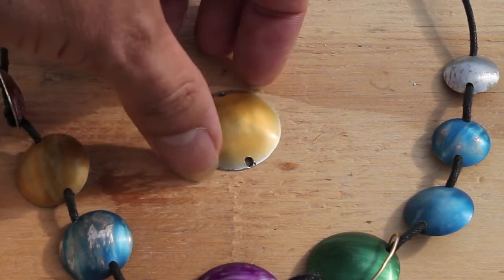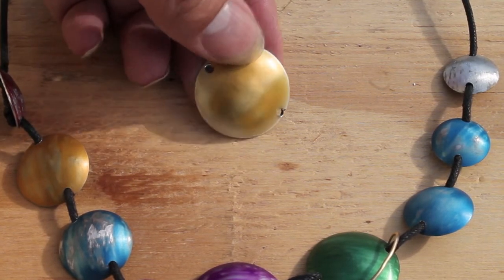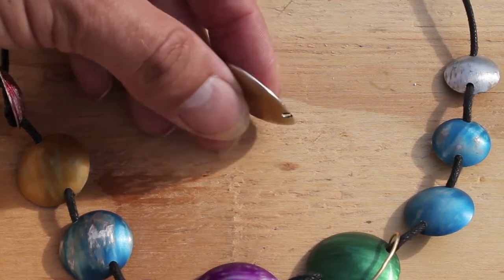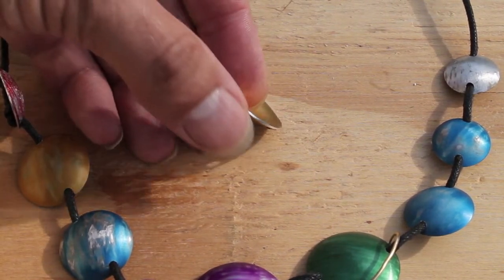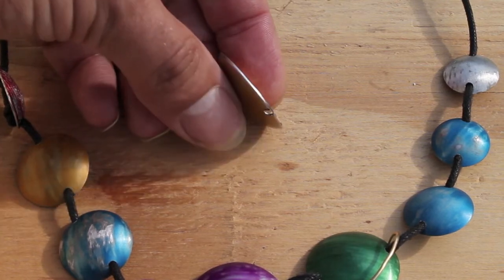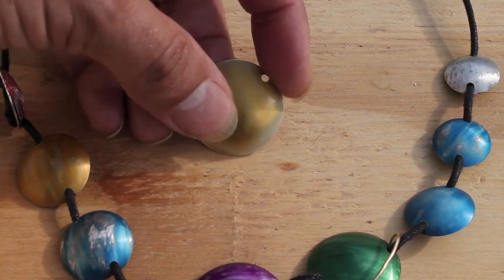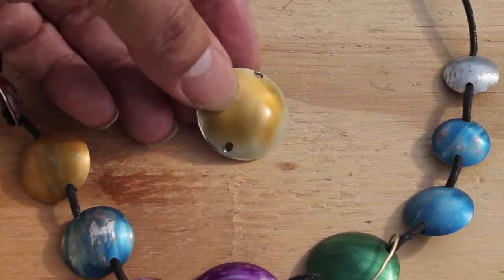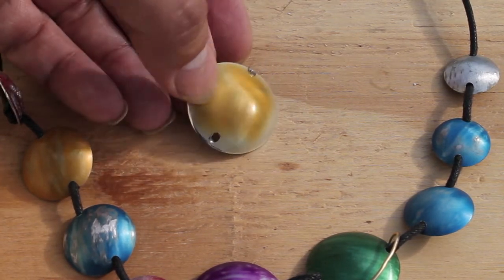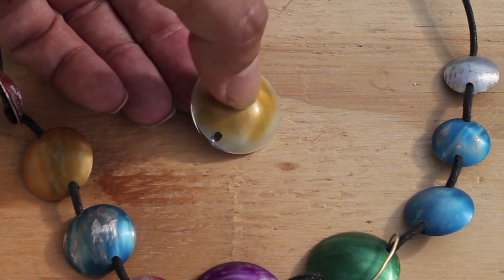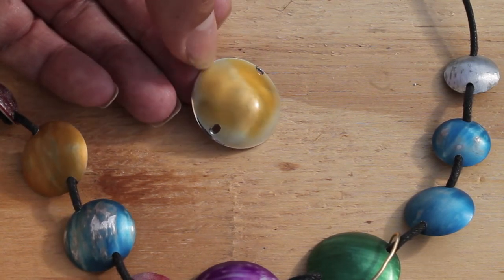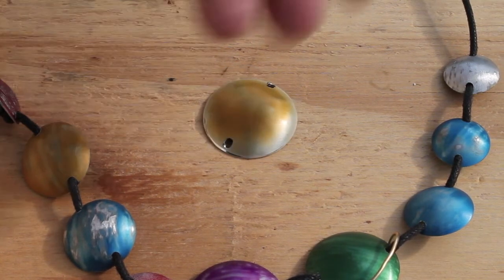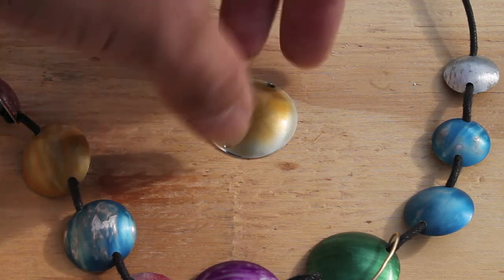This was done with the gold, the big hole there. You can see the difference there before and after. This was put on the bench polisher using some very harsh polish, tougher than Tripoli. There's two things to notice. First of all, the edge has got a beautiful mirror shine on it, almost like silver. And the other thing is, the gold anodizing in the middle fades out towards the edge and you get a kind of slight dull silver color underneath. This is where it's worn out because I've polished it heavier around the edge. That's a nice effect as well.